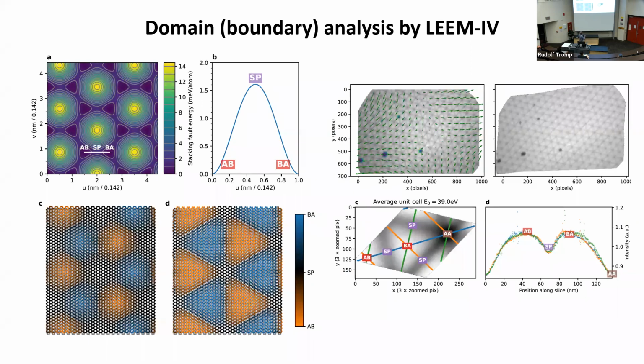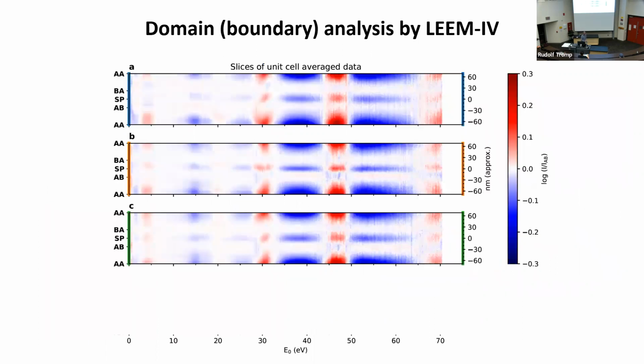Now we're going to take one of these areas of the sample you see here. It's not exactly regular, so we do an affine transformation so that this becomes a perfectly triangular lattice. Then you can do a unit cell average and measure the image intensity across a scan across the unit cell here. It looks like this. So you can measure the image intensity at some electron energy as a function of position. When you do that along the three symmetry directions of the unit cell, you see that the image intensity looks very similar, and they should be because they're equivalent directions.